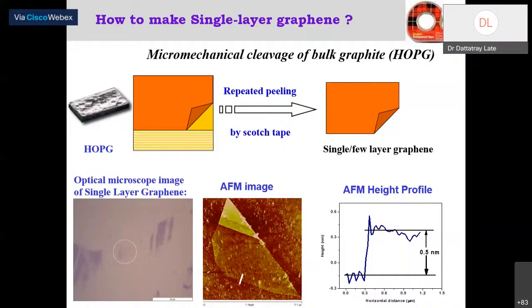And then once I have folded the tape onto itself, I will put that tape onto the SiO2 substrate, which I have already created in any size, maybe 1 centimeter by 1 centimeter, depending upon your need. I can slightly rub the tape on top and take the tape off that substrate. I will straight away go to the optical microscope and see all these color contrasts. You can see this is monolayer.